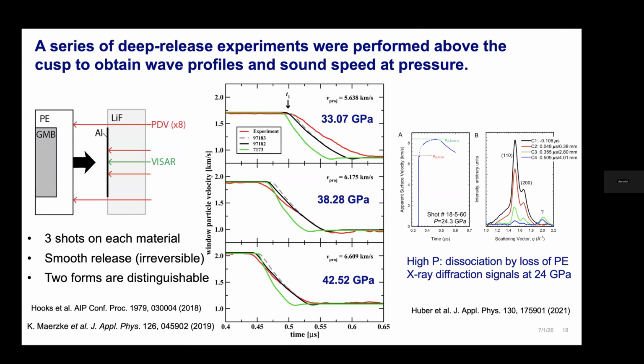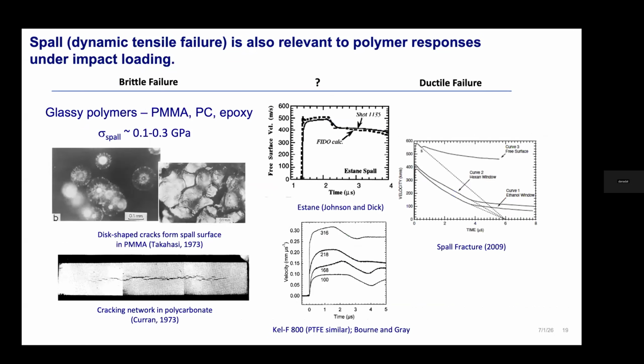I think I'll skip over this one, but just to say that we did experimental techniques to validate those product equation of state by essentially measuring the sound speed at pressure after we've already shocked it into that product regime. And I think the exciting part here, and this B figure is missing, I can't see it, but we took this also to APS and DCS, and if you shock above that cusp, we actually saw the disappearance of the polyethylene peaks. And in some cases, we've seen the appearance of peaks associated with graphitic phases at various pressure regimes. But we do see the disappearance of the polyethylene diffraction once we get above that cusp.